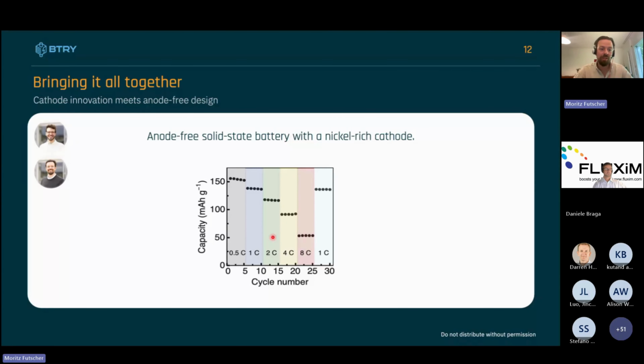And then we brought this together, both Abi and I, and we actually were able to fabricate such an anode-free solid-state battery with a nickel-rich cathode, which Abi developed, and we could show that this performs relatively well. And this was really one of the starting points of the startup itself, where we saw that the performance in the lab works well, and we also saw that there's an interest in industry for such a technology, and this was then the starting point where we said, okay, let's think about starting a company.